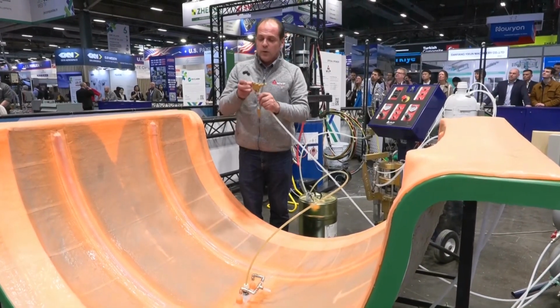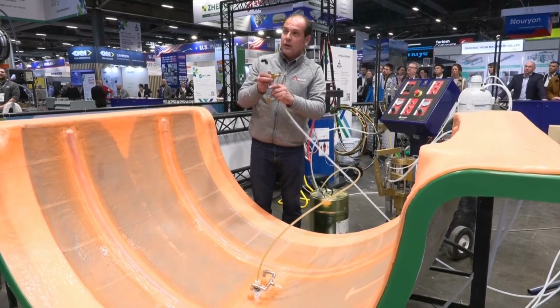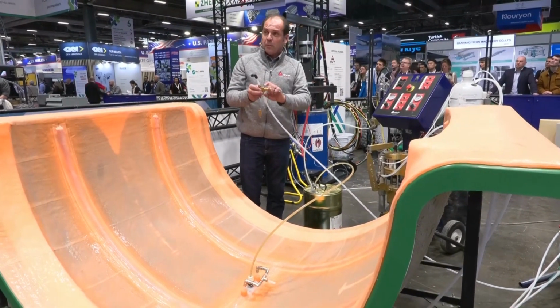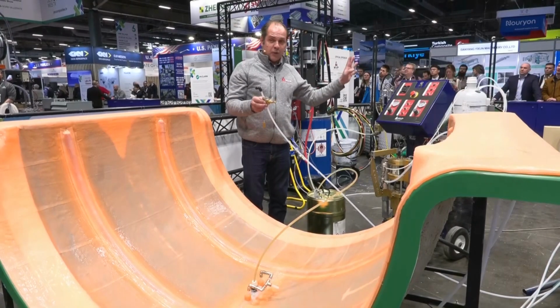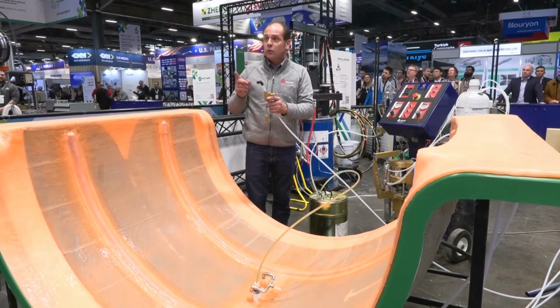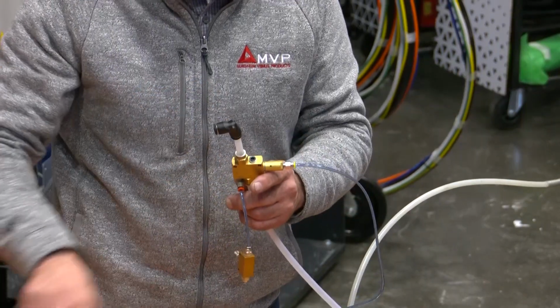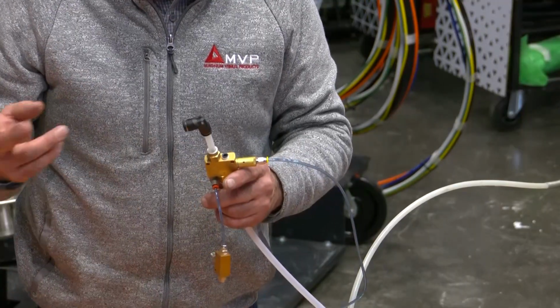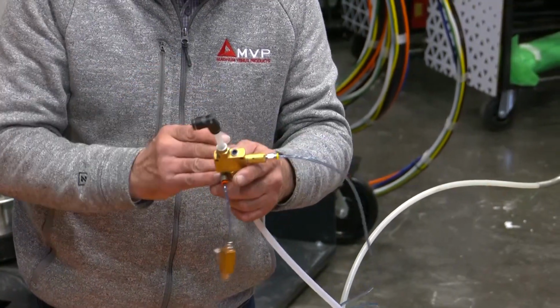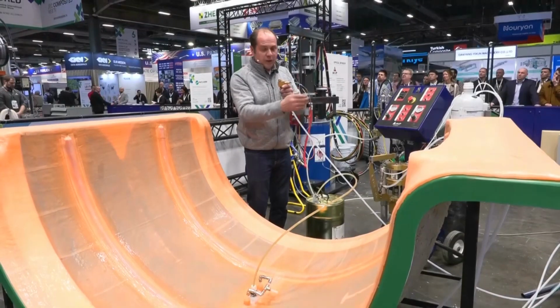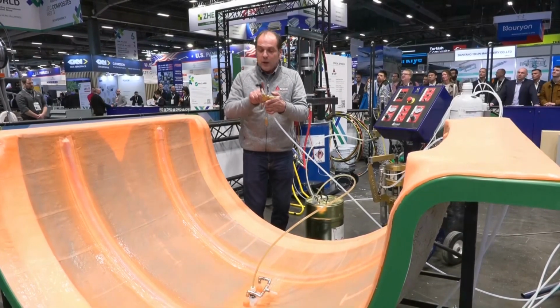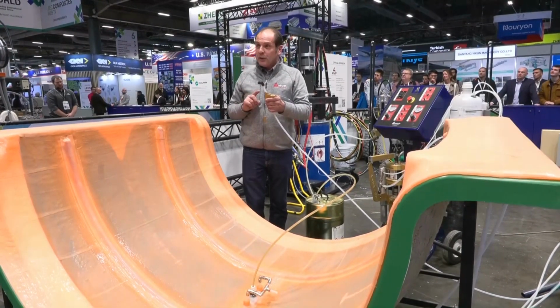Why? Because I use a special vacuum valve. When I start the machine, the valve opens, I pull the vacuum. When I stop the machine, the valve closes. But it's not good enough to close. You have to let the air come into the resin channel. So for that, that valve will close the vacuum, so we don't lose the vacuum on the vacuum pump, but we have the air passing through. And we have better than that, we optimize that.